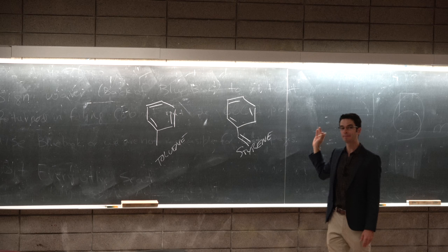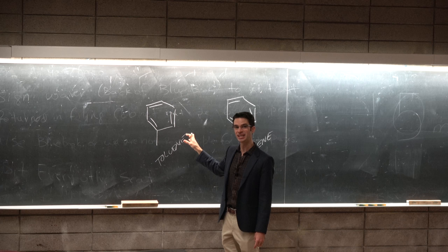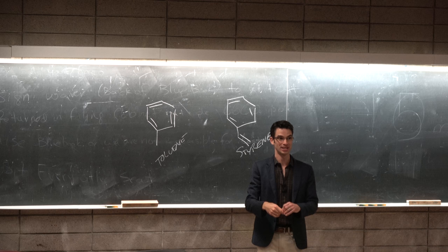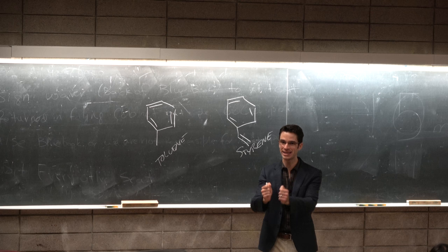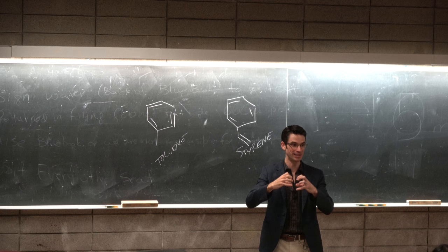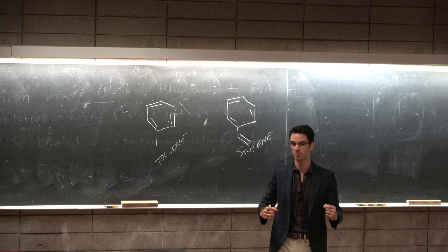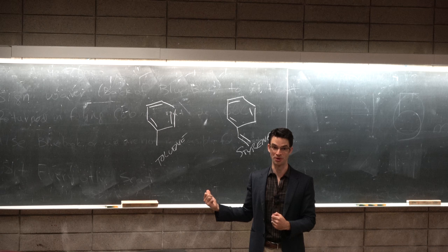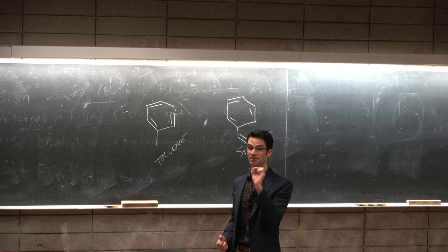And even though the enthalpy of mixing isn't going to change too much, because you still have this interacting with this, which is pretty similar, the change in entropy becomes much, much less. Because by making a polymer, you're confining the monomers. You're telling them that they can't be anywhere. They have to be next to each other. So the entropy of mixing is much less favorable. If you have infinite molecular weight, the entropy of mixing goes to zero, and even the slightly unfavorable enthalpy of mixing takes over and makes them insoluble in each other.